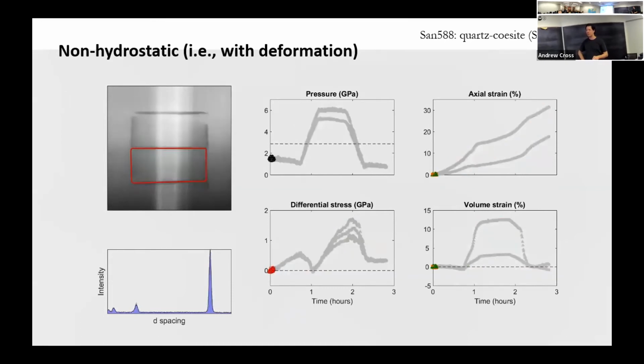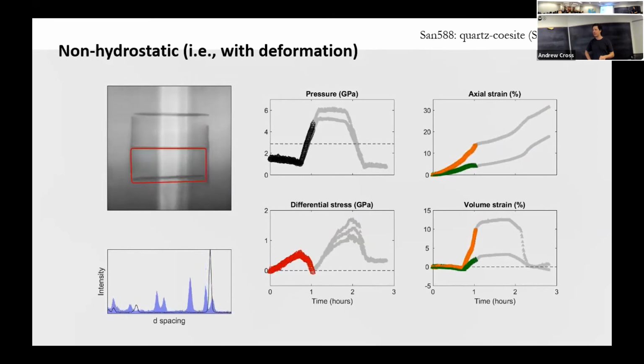The radiographs here are really spectacular. So we're just shortening at a constant rate. You'll see this foil will start coming inwards. And then as we start our pressure ramp, once we go through the phase transition, you'll see an extra little bit of shortening right here. So the sample's not really getting wider, it's only getting shorter.